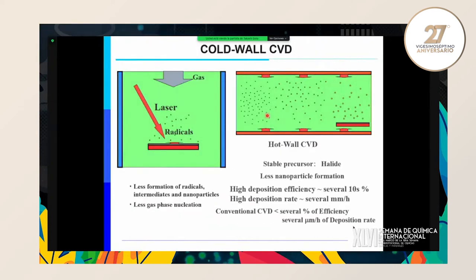But it was not true. In laser CVD, there is less formation of nanoparticles and less gas phase nucleation. So if we use a stable, not so reactive precursor like a halide, deposition efficiency becomes very high, several tens of percent. And the deposition rate becomes several millimeters per hour, even using an organic compound, if it is not so reactive. In conventional CVD, efficiency is several percent or less.